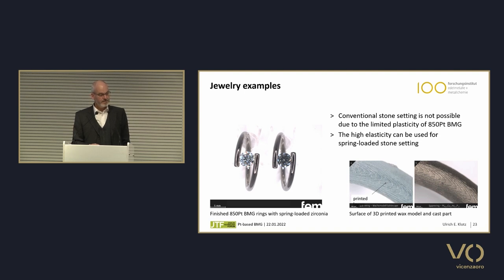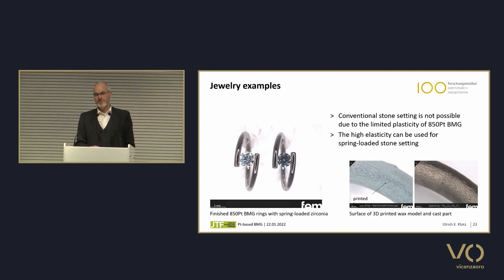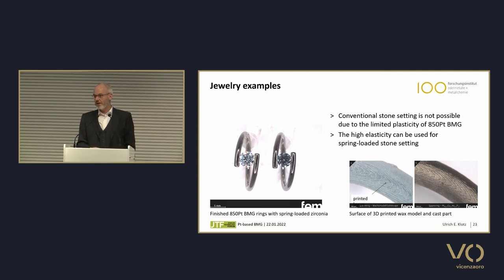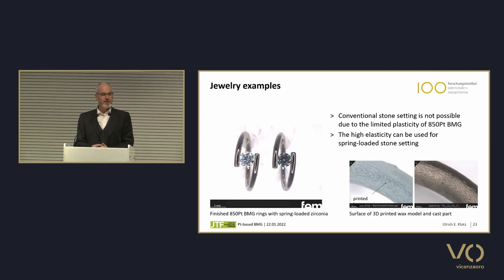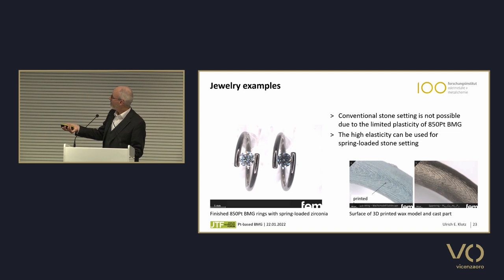And Eike is, as I said, a master goldsmith, and he had a great idea. He wanted to use the elastic properties by mounting a spring-loaded stone. So this is a cast ring, and the edges you can use as springs, but actually these two sides of the ring were bent over each other to mount the stone. So before casting, the right side was the left side and vice versa. So you had to bend the ends over each other, something you cannot do with a conventional material. You would just bend the ring, but because the material is so springy, it's working really well to fix the stone like this.